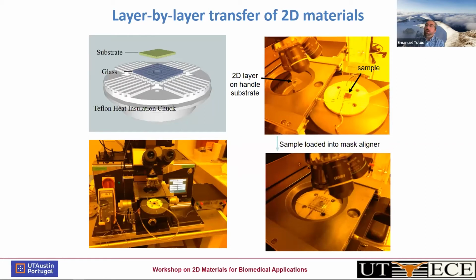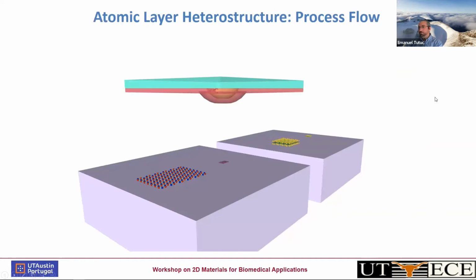The one way to implement this is to use a mask aligner. So the hemispherical handle would be somewhere here, and then the sample with the 2D layers would be here. We load it in the mask aligner, and then we make use of the micro manipulation in the X, Y, and Z direction that the mask aligner allows. But since then, we've also implemented a setup with other types of positioning mechanism.